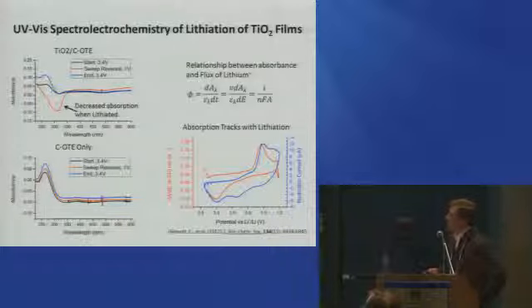So this just shows the absorbance as a function of wavelength. And you can see that out here in this near-infrared part is where most of the absorption increases when you lithiate. So Tom talked about this. This is basically this Drude edge-like behavior where you have these free electrons in the conduction band. And in the gap of this, the gap is actually attenuated. So it looks like it gets a little bit bigger, and so the absorption goes down. You can't do this on ITO because ITO interferes with this.